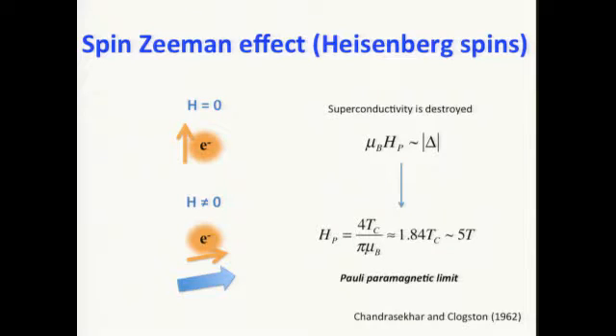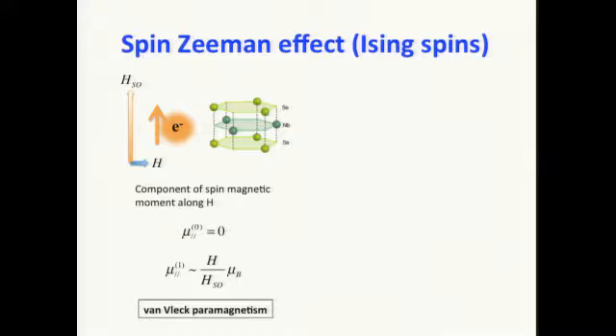Okay, but you may remember that I told you even up to 20 Tesla superconductivity still survives in this material. Then actually, in the case of Ising spins in this kind of material, the spins are locked by this huge spin-orbit field to the out-of-plane direction. So if you apply an in-plane field, 30, 40 Tesla is still very small compared to a 1,000 Tesla spin-orbit field. So in the zeroth order limit, the spins just don't respond to the applied magnetic field. So the magnetic moment is 0.